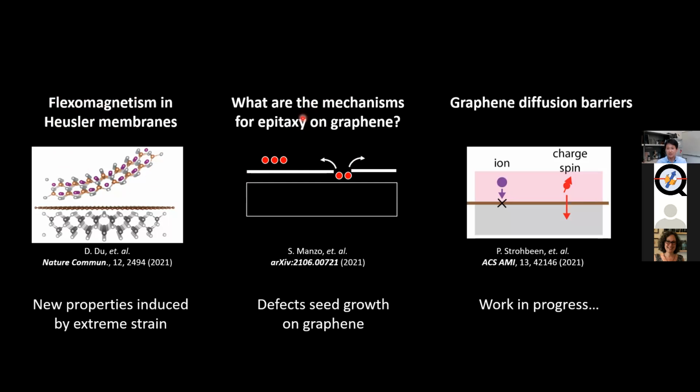In the second part of the talk, I gave you some insights into our atomic-level understanding of how this growth process on graphene works. We think that in most experimental cases, it's not these idealized remote interactions that are dominating the growth, but rather it's these pinhole defects that are seeding a lateral epitaxy growth mode. And this is important as we're thinking about how to apply remote epitaxy-like approaches to new kinds of materials, and it also tells us a little bit about some of the limitations you might expect if the growth process requires pinholes. At the same time, we haven't strictly ruled out a remote mechanism, so I think there's a lot more work to be done in really understanding opportunities and limitations of this approach in general.